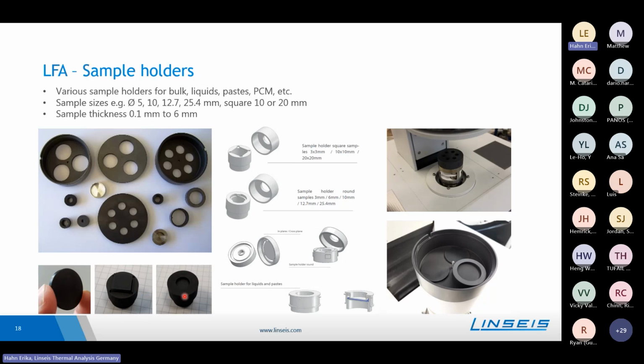Then this will be covered with a lid to avoid that any light or laser light will come through the sides directly to the detector. It will be placed here in the sample robot like that, covered as well with a lid to have a homogeneous temperature distribution within the sample container. And then we can close the furnace and do the measurement.